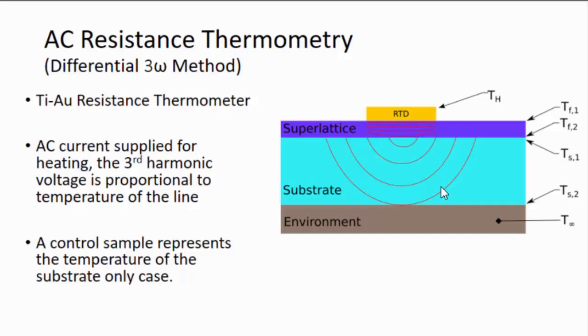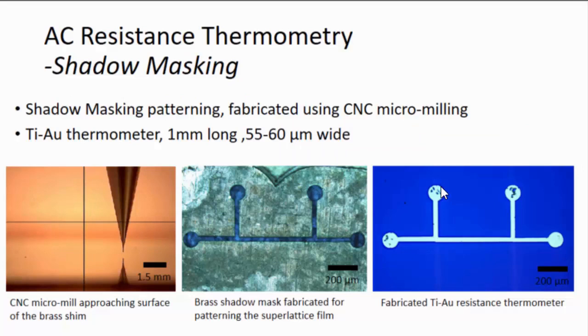Because our superlattice structure was comprised of PMMA, which is solvent sensitive, we weren't actually able to use any of the conventional lift-off based patterning techniques. So instead we opted for a shadow masking procedure, which we fabricated with a CNC micromill. Over here you can see this is a 50 micrometer diameter end mill cutter approaching the surface of some brass shim. We then use this to cut a negative of the resistance thermometer shape that we wished into the surface of the brass shim. We then pressure mounted this to the top of our samples and evaporated titanium and gold through that.